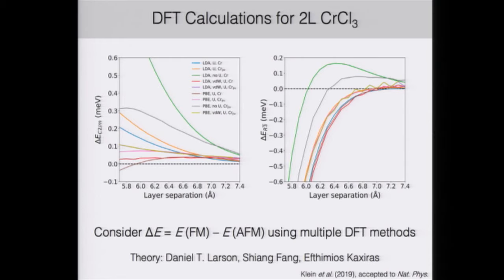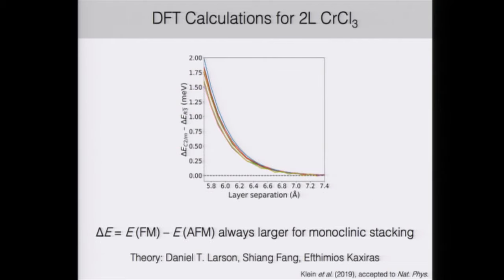We further collaborated with Tim Kaxiris's group here at Harvard with Daniel Larson and Shiang Fang in order to look at DFT calculations for chrome chloride, similarly to what was done for chrome iodide. So what they did was they looked at the energy difference between the ferromagnetic and antiferromagnetic states as a proxy for the antiferromagnetic interlayer exchange. And so they looked at both the monoclinic phase and the rhombohedral phase and used a large number of different DFT methods. But what they found is that regardless of the DFT method used, the energy difference between the monoclinic and rhombohedral phase always showed a larger antiferromagnetic exchange for the monoclinic stacking.